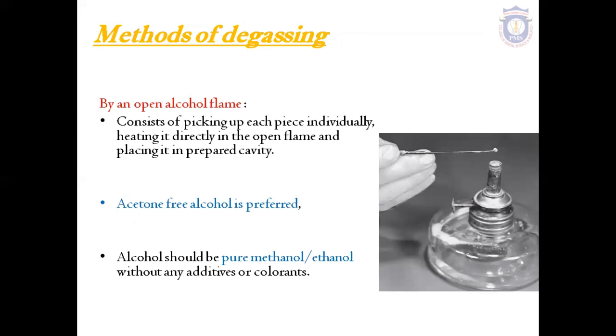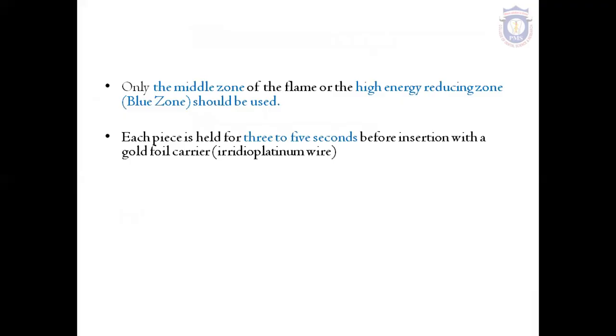The methods of degassing. By an open alcohol flame, it consists of picking up each piece individually, heating it directly in the open flame, and placing it in the prepared cavity. Here, acetone-free alcohol is preferred, and the alcohol should be pure methanol or ethanol without any additives or colorants. Care should be taken that only the middle zone of the flame, or the high energy reducing zone, should be used. Each piece is held for 3 to 5 seconds before insertion with a gold foil carrier. The time is 3 to 5 seconds.